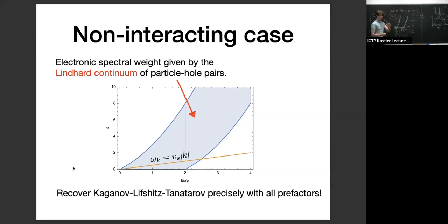By the way, just for phonons, we're never up here, right? The phonon line is very, very flat. So this region is not relevant for phonons ever. So the phonons are basically at zero as far as the electrons are concerned. So when you calculate the rate of decay into phonons, most of the decay comes from large wave vector electrons, because you have to do all the electrons emit all the particle hole pairs. And so most transitions that emit phonons are these large wave vector ones, and they don't see the interactions so strongly. The interactions are here. However,